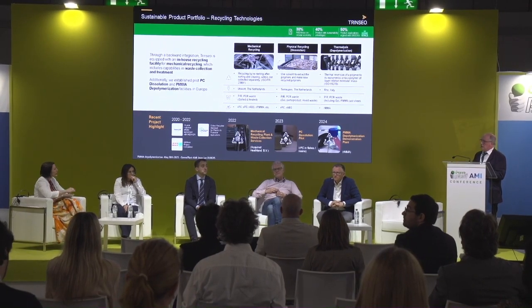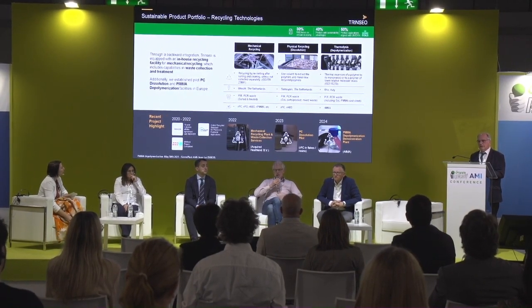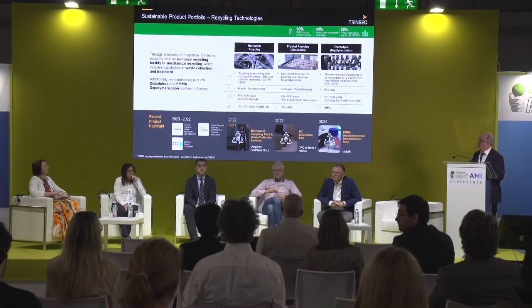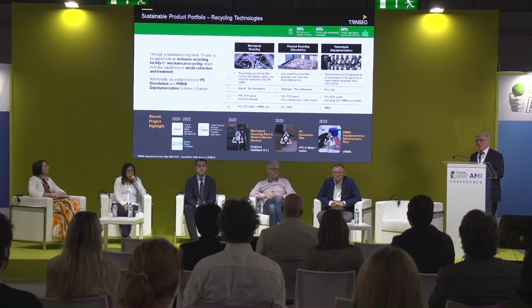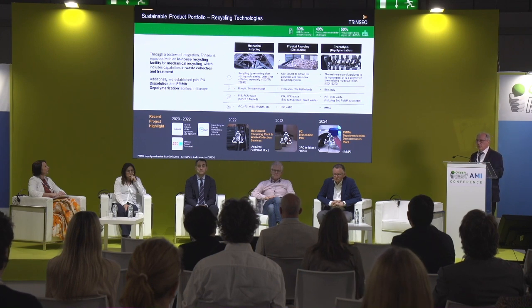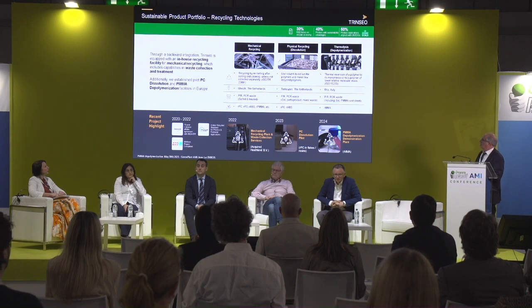The other activity in Trinseo in Netherlands is related to a selective dissolution type process for polycarbonate and ABS. In this technology, a specific solvent is used that dissolves specifically the targeted polymer and not the other one, and after, the polymer is recovered by precipitation.